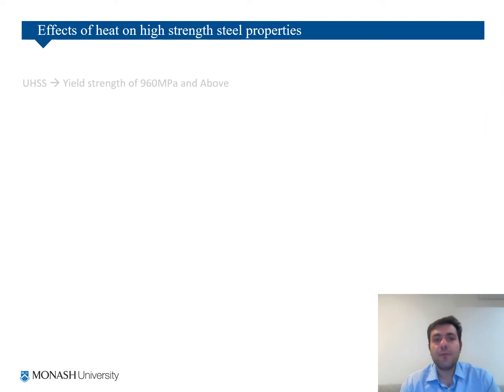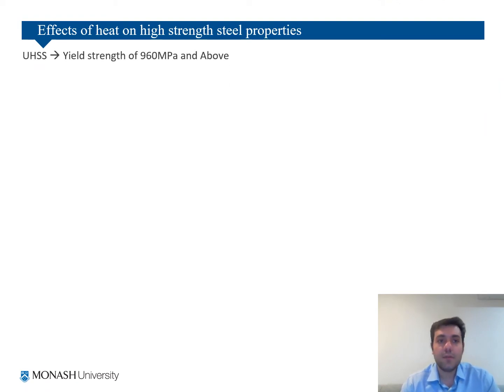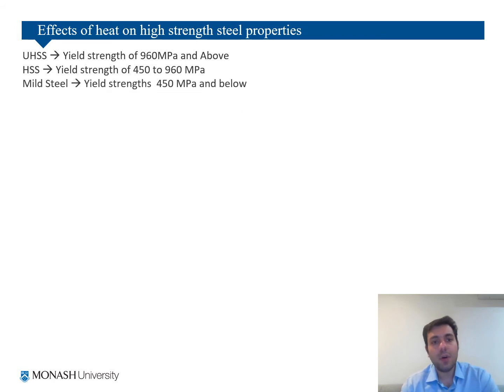So we have different types of steel materials. We have ultra high strength steels with yield 960 and above, high strength steels from 450 to 960 MPa, and mild steel at or below 450. So the first one, ultra high strength steel, gains that strength from a special heat treatment technique. They call it direct quenching, or quench and tempering in different scenarios.